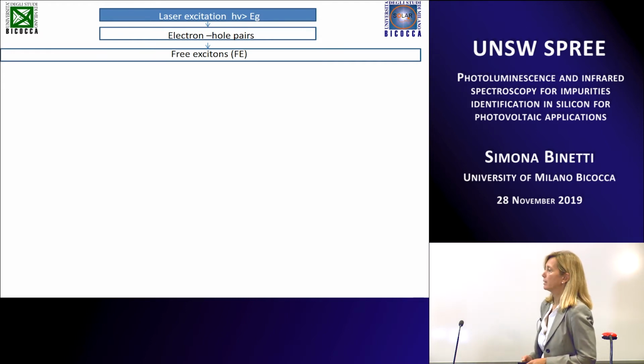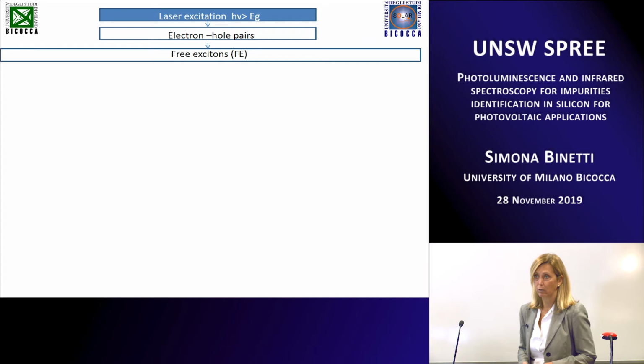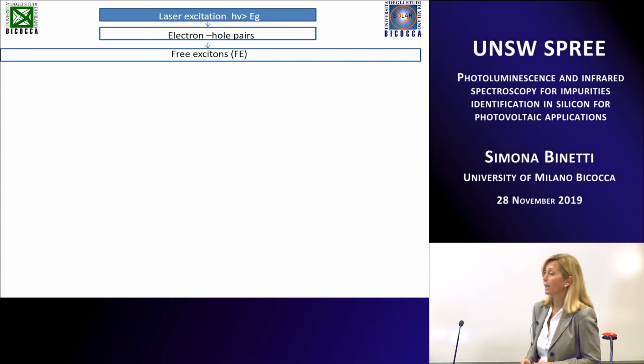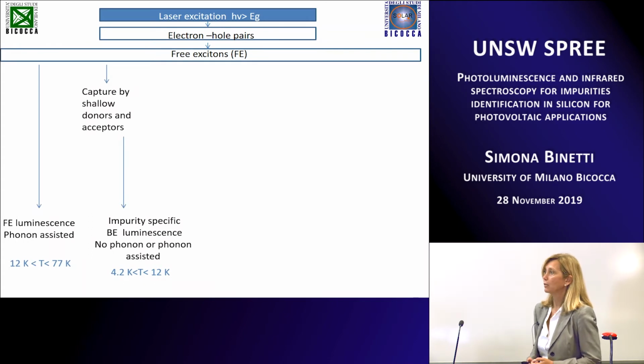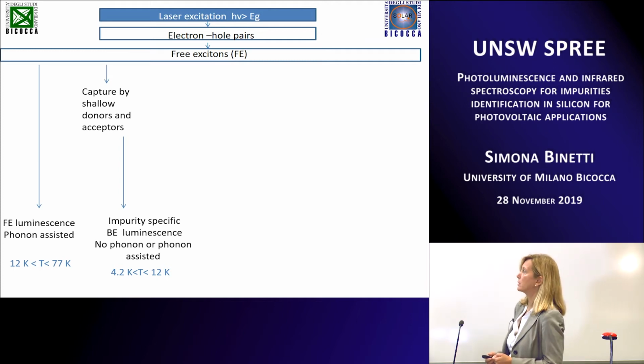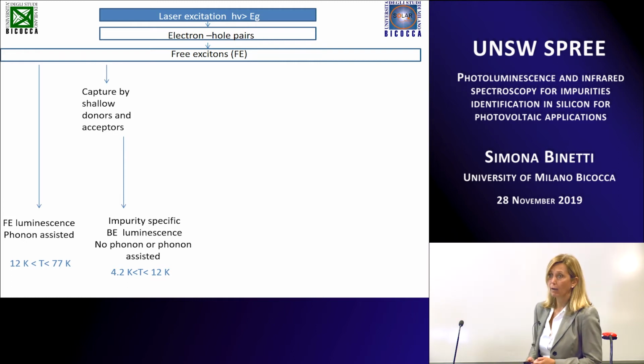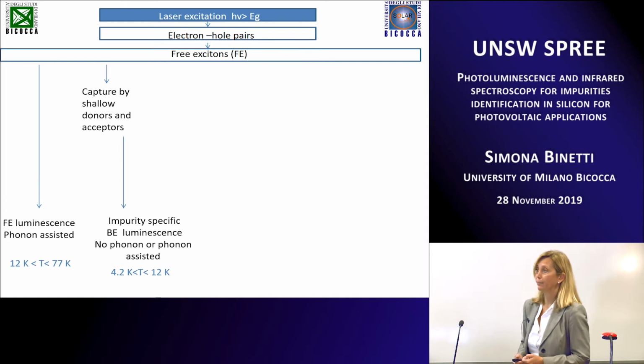If you heat the silicon with a laser excitation with energy higher than a band gap, you can create, of course, electron and hole pairs. And if you are at low temperature, they can form quasi-hydrogenic particles that are the free excitons. Then, at low temperature, the free exciton can recombine, emitting a free exciton luminescence that is phonon assisted and can be detected in between 12 Kelvin and 77 Kelvin, or at lower temperature the free exciton can be captured by shallow donors and acceptor and can give rise to impurity specific bound exciton luminescence, non-phonon or phonon assisted.